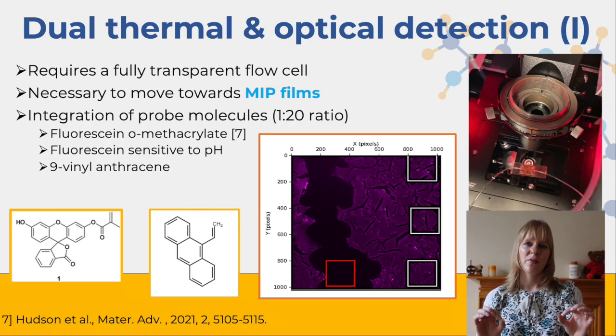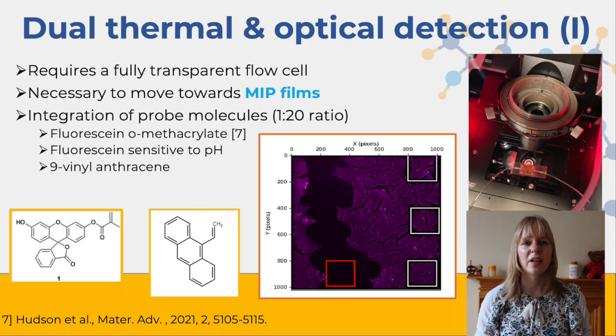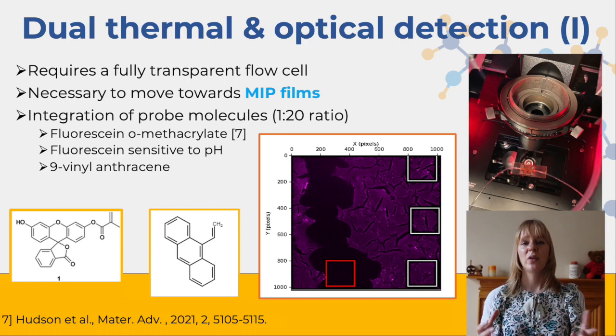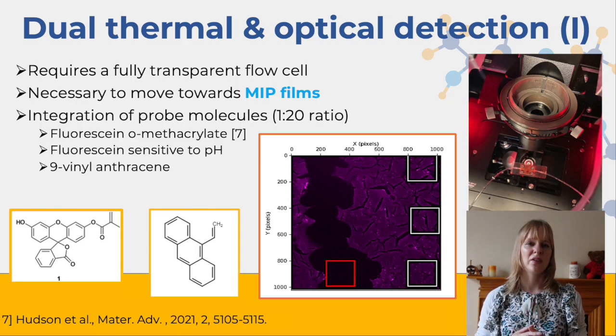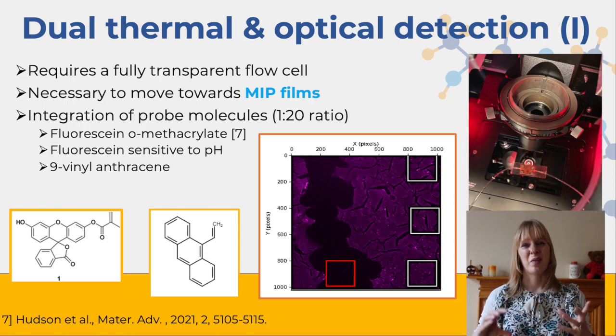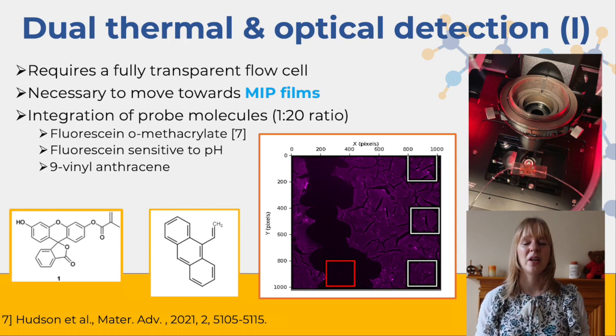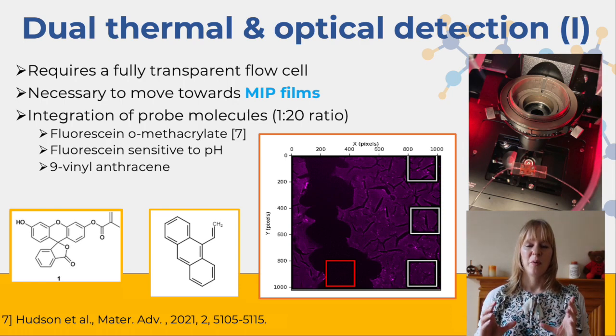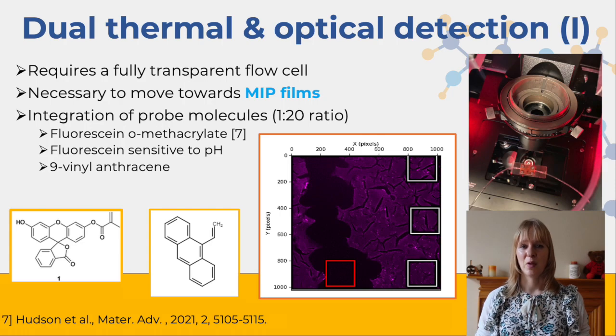And the other difference that we had to make in order to facilitate this optical detection is we had to integrate an optical probe. Initially we looked at fluorescein, which was less suitable because fluorescein unfortunately does very easily respond to environmental changes, and particularly changes in pH. And water can have a very wide range in pH. Then we started looking at anthracene as another optical probe. There's many others that you can use, but we thought that would be a very neat way of combining the both.